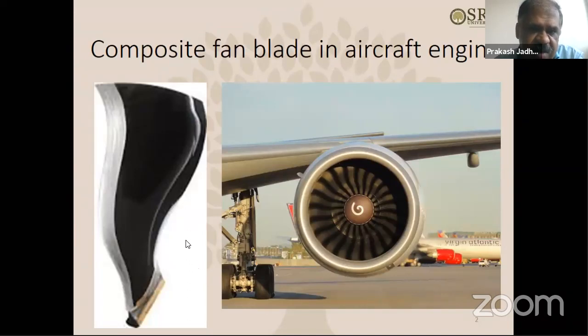So basically, it's a solid carbon composite. The thickness goes to maybe around 20 millimeters at the center or something like this. So can we use some kind of structural foam insert inside so that the weight can be further reduced, but without affecting the performance of this fan blade? Performance in the sense that under the mechanical loading and also under the bird strike loading, it should still qualify. That was the condition.